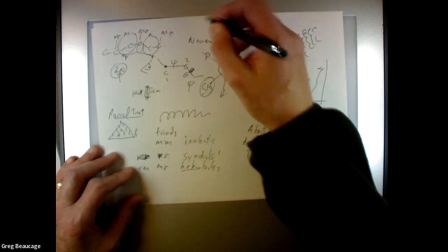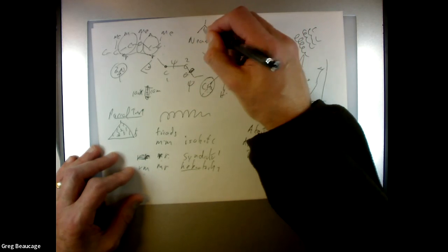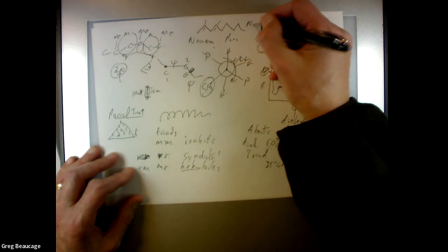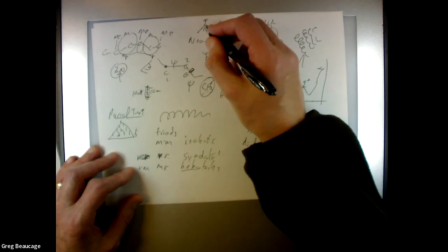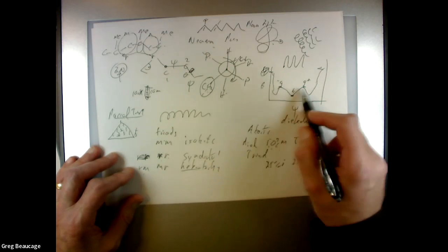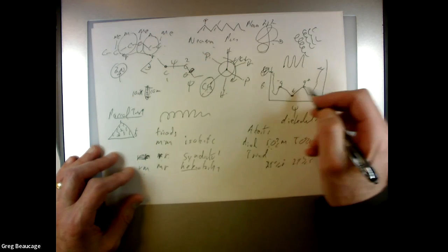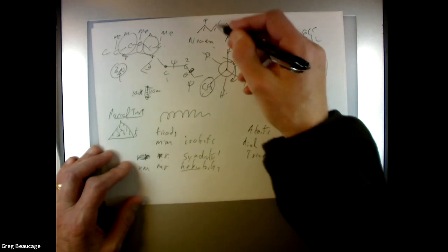For polyethylene, the helix is the simplest helix. It's actually in the plane of the paper. That's actually polyethylene. And then the H's stick out, but the backbone is a planar zigzag. If you stick a methyl group on that, it gives it a kink. Like this energy diagram isn't symmetric anymore. So when it tries to form that planar zigzag, it can't do it. It has to move out of the way a little bit. And it does that the same way every time, and it makes a helix.